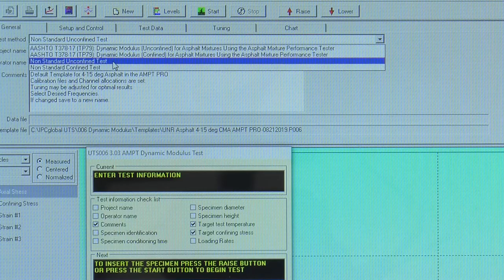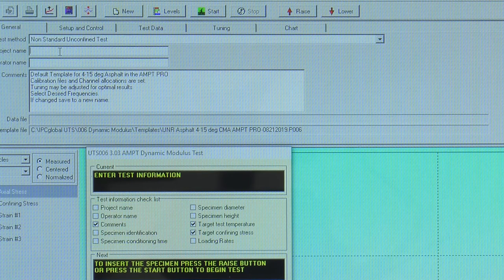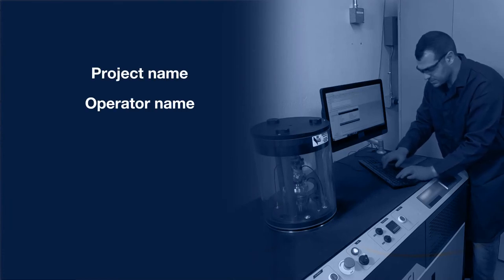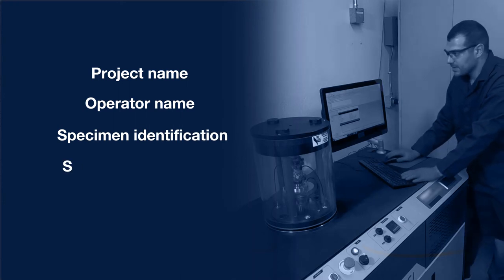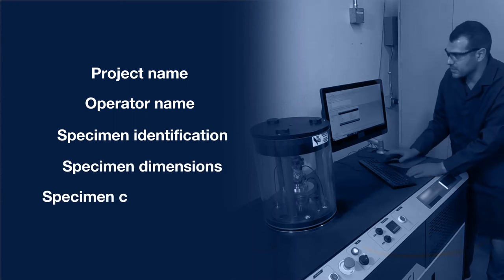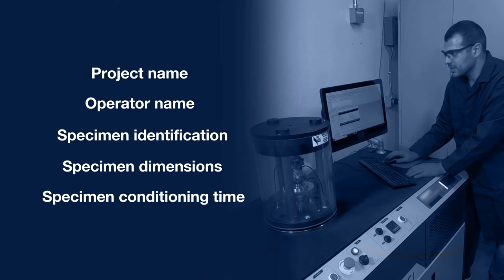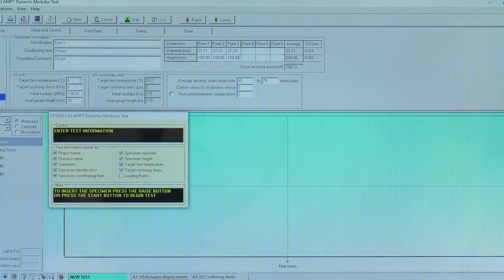Select the appropriate test template. Enter the specimen identification and control information into the Dynamic Modulus test template. The information may include project name, operator name, specimen identification, specimen dimension, specimen conditioning time, and comments like air voids. Check the target test temperature and initial modulus on the test control software. The initial modulus should be representative of the region's typical values of asphalt mixture use at test temperature.